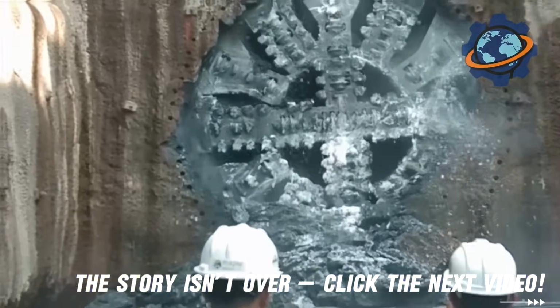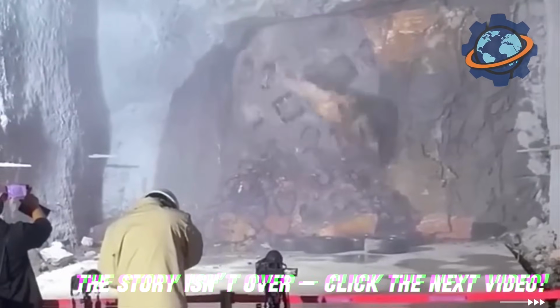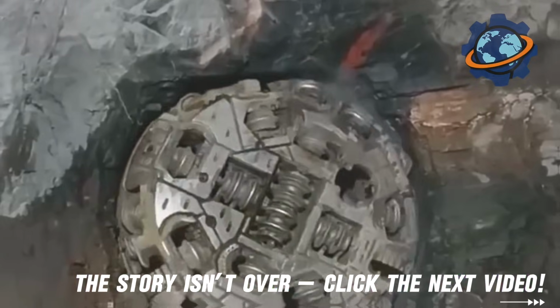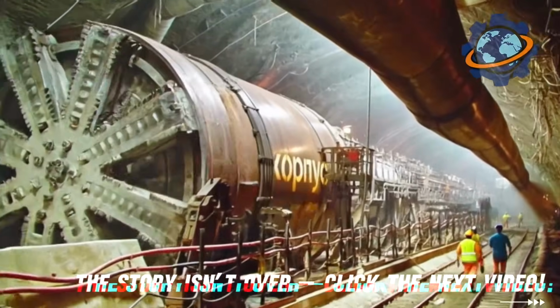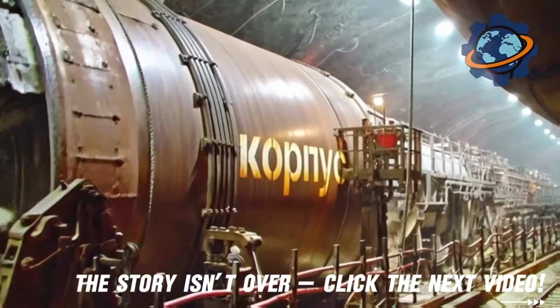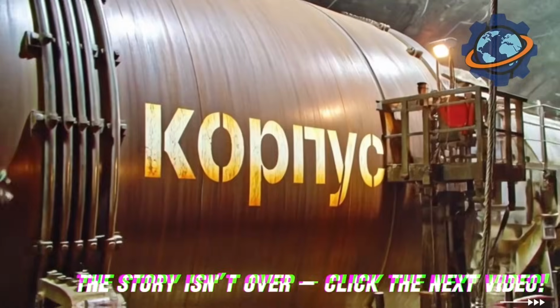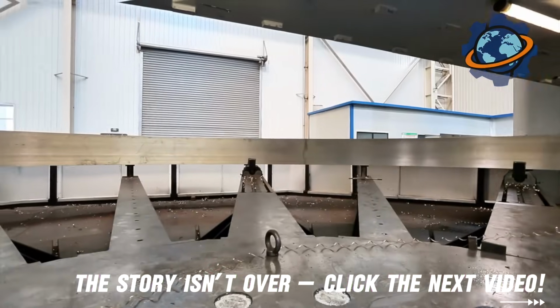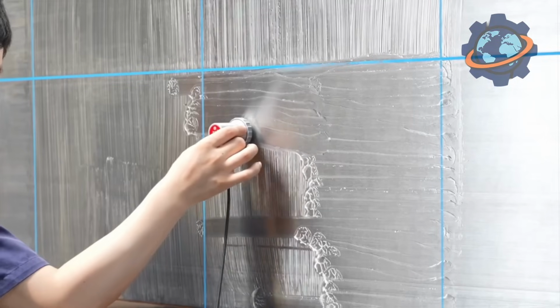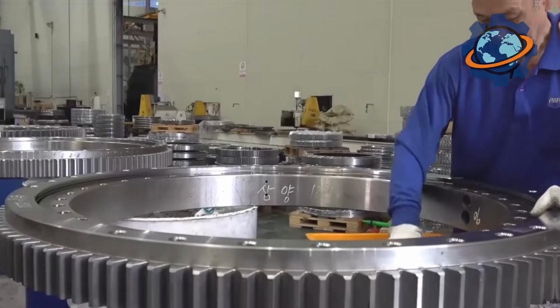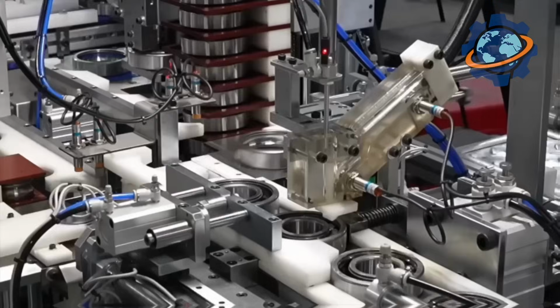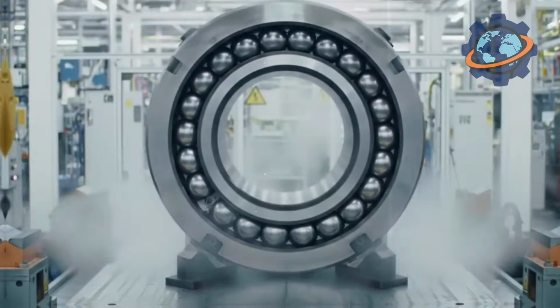If the bearing surfaces are uneven, even by a few thousandths of an inch, stress concentration zones appear. Metal at those points starts wearing down, heating up, and the bearing will fail. For large bearings, a segmented design is often necessary. A bearing over 30 feet in diameter can't be made in one piece. It simply won't fit in any heat treatment furnace.